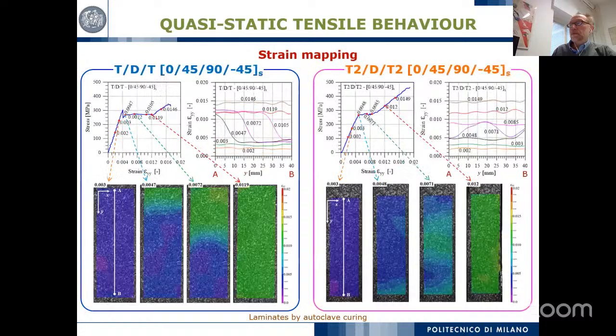And this could be visible also for the quasi-isotropic laminate, with this delamination that starts and slowly moves through the specimen, which is different than the other sublaminate. I would also give a comment on the difference between this thick ply and the thin ply that you can see in the literature.